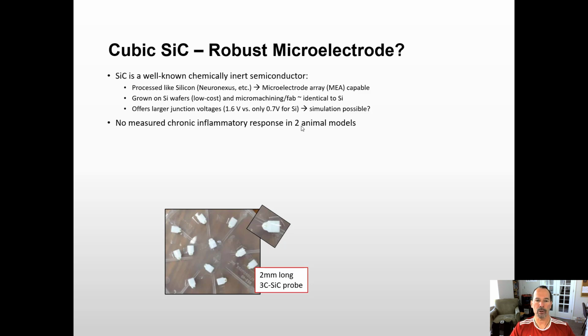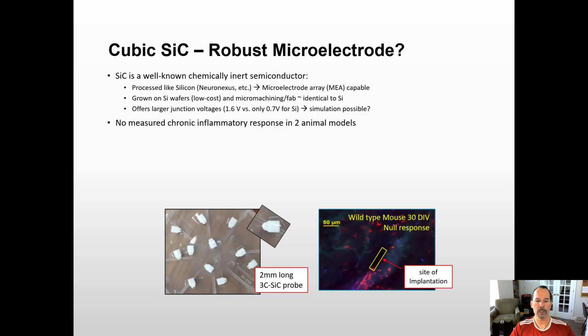So we haven't seen, actually in 3 animal models, this slide has a mistake. We've never seen any chronic inflammatory response. And here's a sample of that. This was 1 month in vivo in a wild-type mouse. And at the site of implantation, it was difficult for Dr. Fruin, who's one of my former students now working at NeuroNexus, he had a difficult time even finding where the hole in the tissue was, where the implant was located. Whereas for the silicon probes, it was rather easy. There was a bright microglial response all around the probe, and there was neural tissue loss for the silicon control, which I'm not showing here. So we're seeing pretty much null response after 30 days, which is quite exciting.